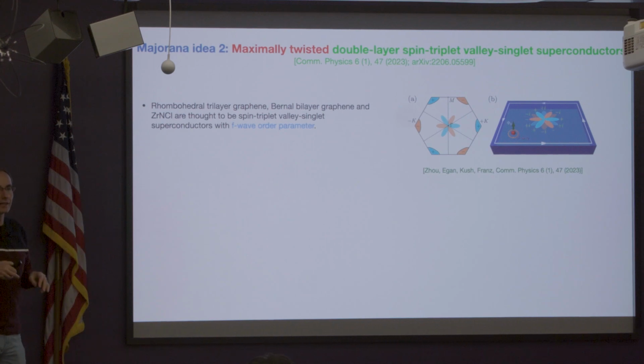So these are experimental facts. And those superconductors break this Pauli limit, sometimes by factors of 10 or so. So they are definitely unconventional. And that led to this idea of spin triplet valley singlet superconductor with F-wave order parameter. Let me emphasize that this is not confirmed. This is just a theoretical idea that sort of fits all those facts.